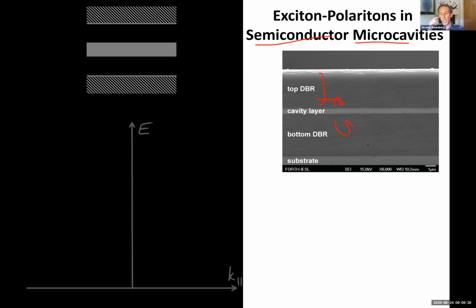So these structures have something like over 100 layers grown, and it takes about 24 hours to grow them, but they're atomically perfect. So this is a very nice cavity. It's on the order of only a few hundred nanometers wide. So it traps light in there. And then in the middle is the cavity layer. And what we can do is put particular thin layers which absorb light very strongly and emit light. So this is the first very nice excitonic polariton system.